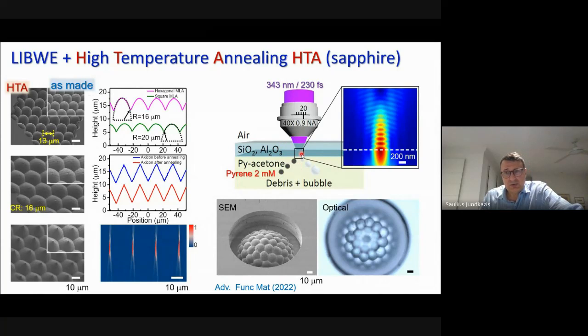What is good about focusing on the backside is that the highest intensity will always be on the interface. Even when you begin to ablate and cut your material, on the interface you will have maximum intensity. If you are focusing on the front side, the highest intensity will be at lambda/4. It will be reflected light, which makes interference, and the maximum is just above the surface, but not exactly on the surface. If light propagates from high refractive index to low, this is the condition which is required so that you deposit energy exactly on the interface. So this is very welcome for machining, but still, after fabrication, it's never perfect.